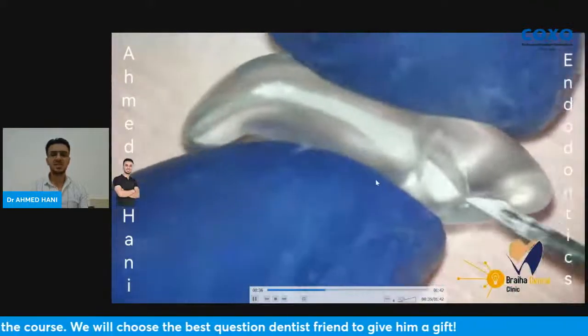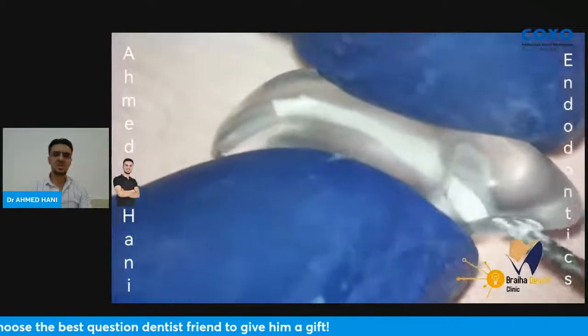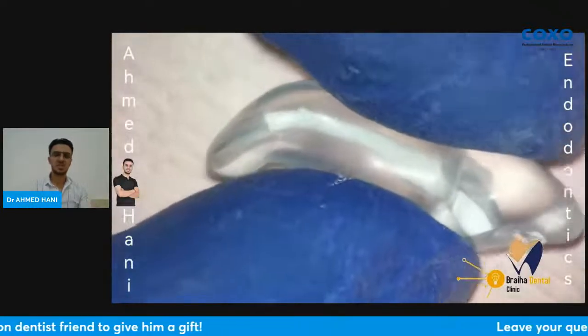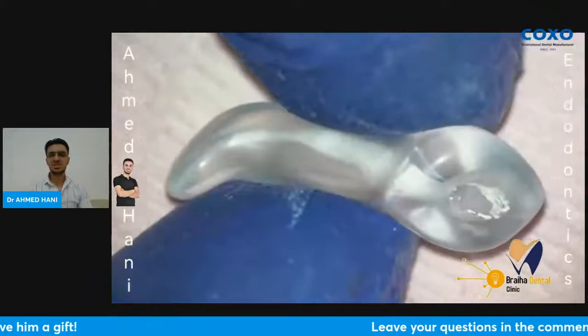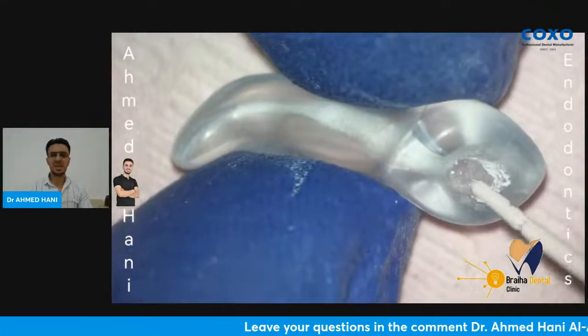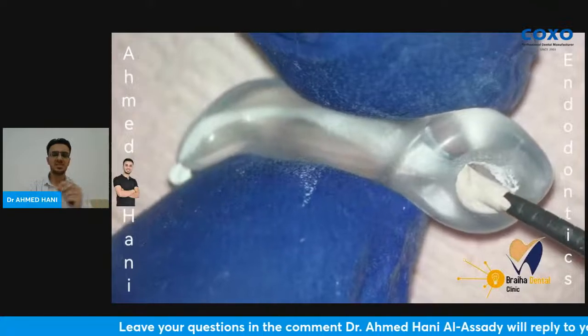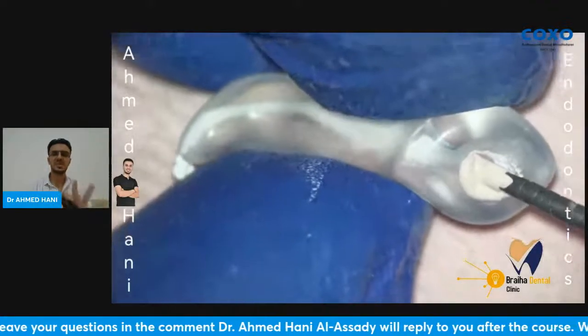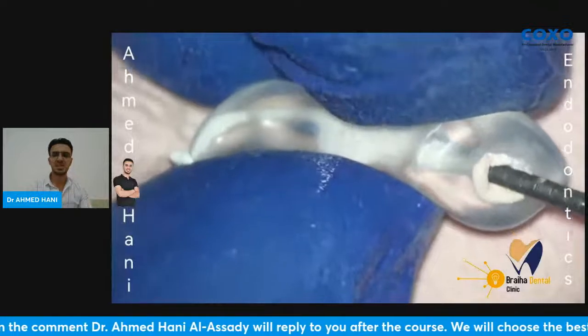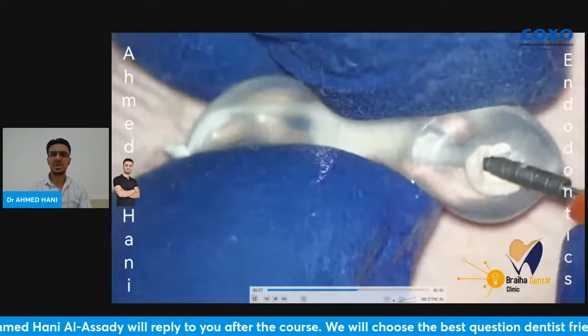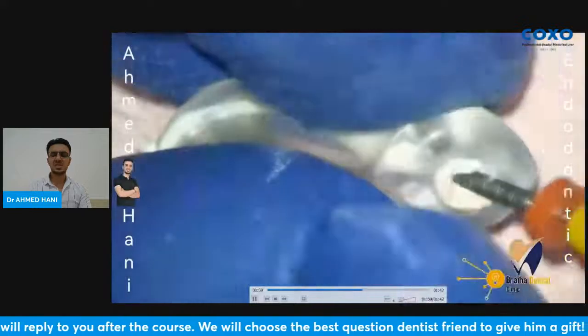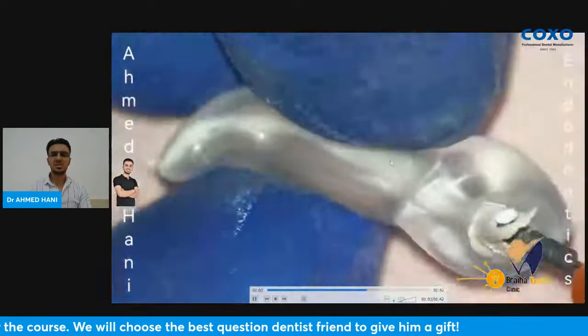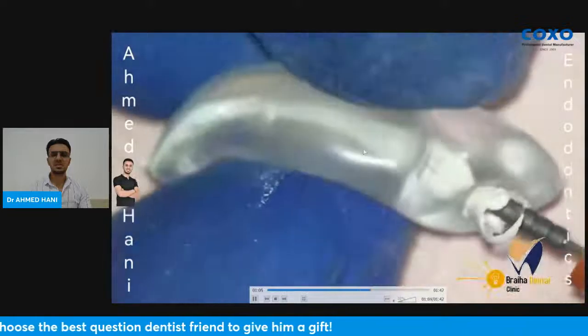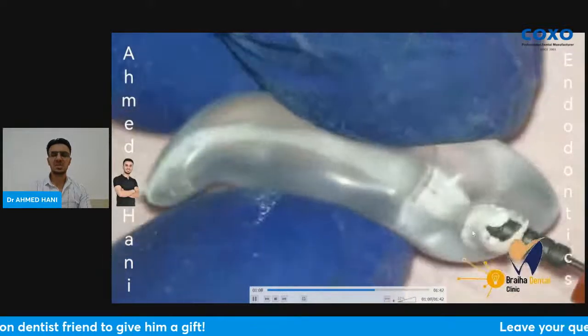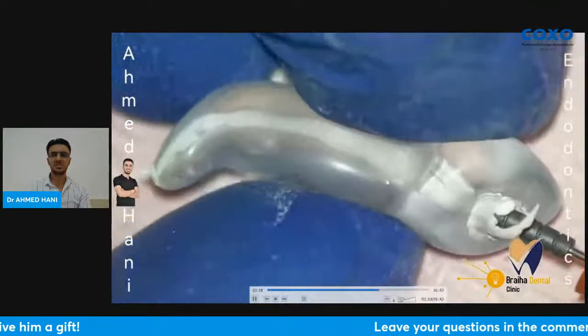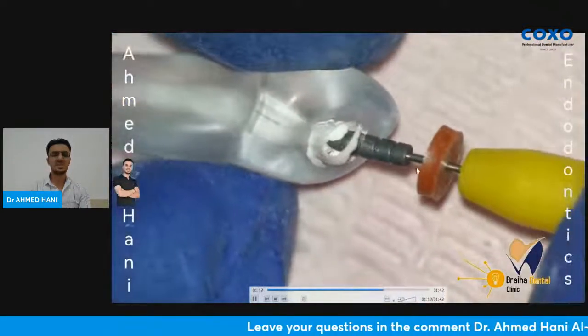And this time I put my carrier-based obturation cones in their special oven. When there's an alarm, just like a beep, it's ready. I take it from the oven and insert it within 10 seconds, within 10 seconds inside the canals. I have just 10 seconds until the cone is cold, and the gutta-percha becomes cold, not hot or molten. So after 10 seconds everything is okay.